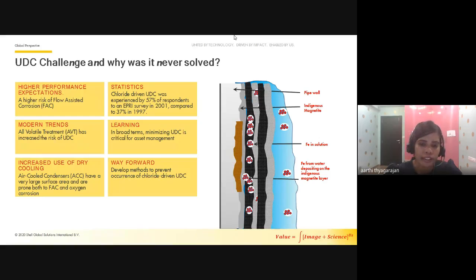Beneath this layer, a process called wick boiling leads to a very high concentration of any ionic species that is present in the steam generator water. As the deposit becomes thicker, the degree of concentration beneath the deposit increases and can reach factors as high as 10,000 times the bulk concentration. At some point, the concentration reaches a critical threshold level and causes the initiation of what we call underdeposit corrosion. Now, depending upon the initial composition of the steam generator water, this may be of the three types mentioned above.